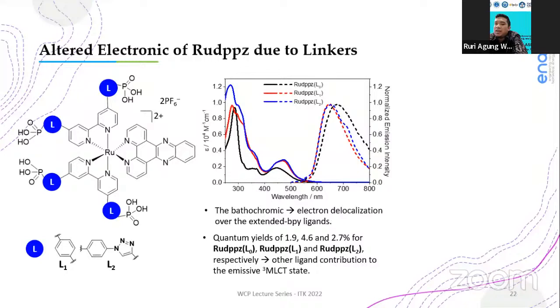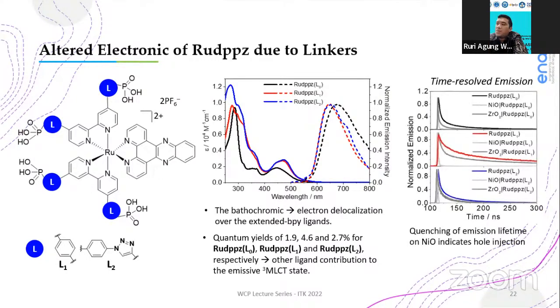So to quickly check that this complex works for nickel oxide photocathodes, we performed time-resolved emission spectroscopy for both dyes in solution, on the inert surface of zirconia, and also on nickel oxide. As can be seen here, the emission lifetime of the dyes in solution is rapidly quenched when the dyes are adsorbed on the nickel oxide surface. Meanwhile, the emission lifetime is slightly shorter on the inert zirconia surface, where charge injection should not take place. Therefore, in this measurement, the rapid quenching of the emission lifetime indicates that hole injection occurs at the interface of the ruthenium-sensitized nickel oxide surface.